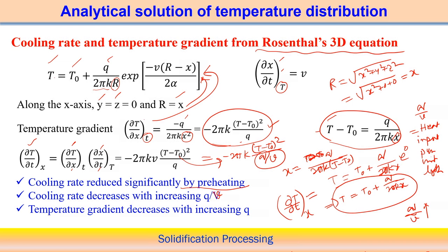And the other part is that the temperature gradient also decreases with increasing Q. As Q is increasing, that means heat input is increasing, and the temperature gradient also decreases. So we have some relation between these parameters. We can make some conclusion, it is a simple analogy. Just following this simple calculation, the Rosenthal 3D equation, we can say all these three are important, which is basically able to correlate the microstructure associated with the different welding processes, depending on whether the heat input is low or more. Based on that, we can make some conclusion with this analysis.